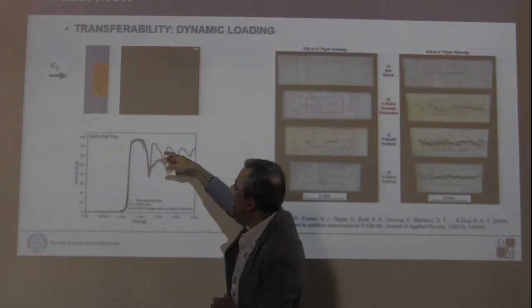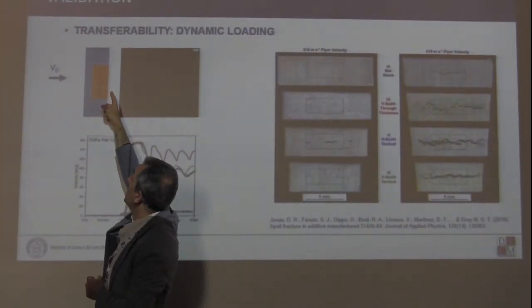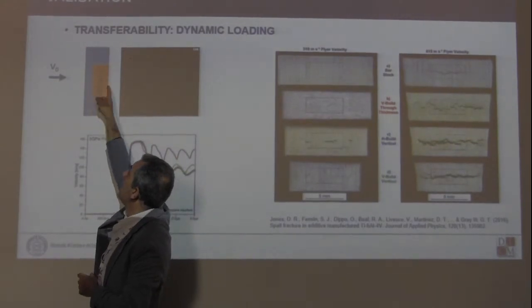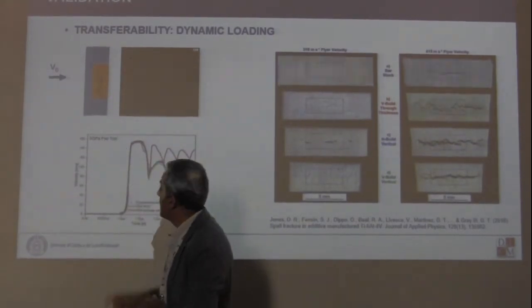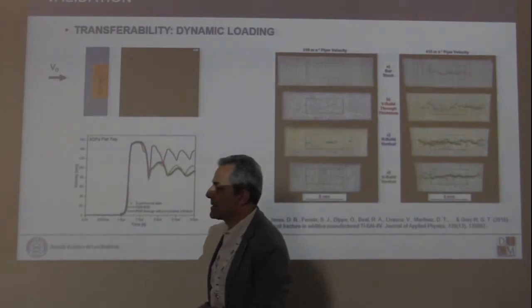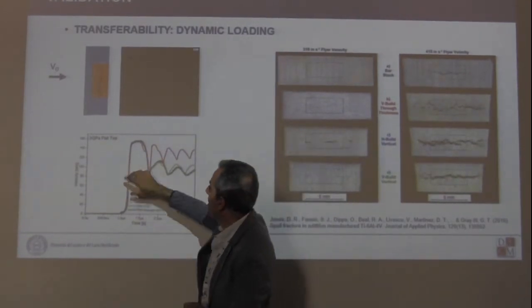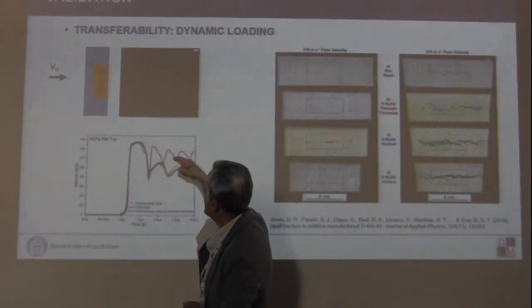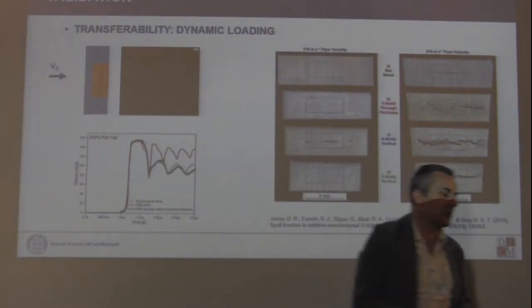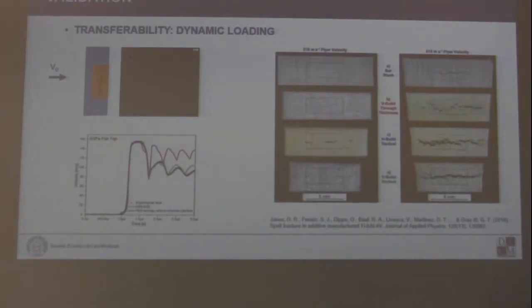During this test, you can measure using laser interferometry the displacement of the free surface, and have this trace. The question is that as soon as you have fracture, you have some release waves coming into the problem. And this is a very interesting test case, because here you have strain history, pressure waves going back and forth in the material. We know exactly the time where damage develops.